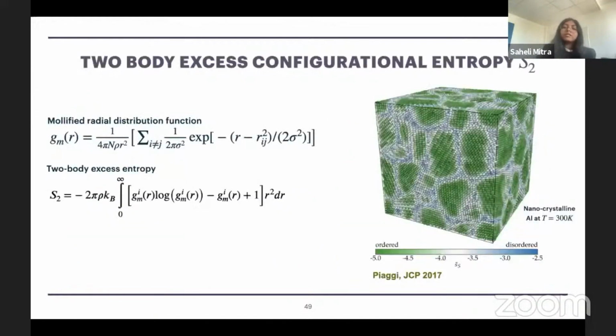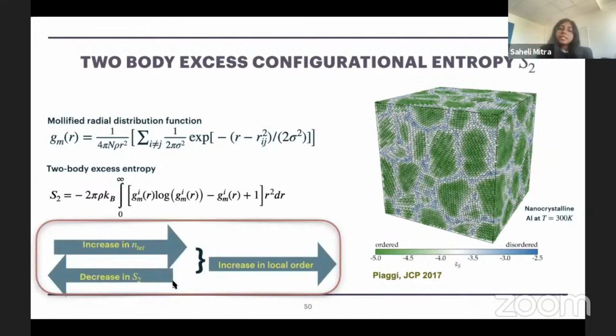Now, the other structural descriptor of our choice is the local entropy S2, which can be calculated from the integration over the local radial distribution function. On the right, I am showing one example for nanocrystalline aluminium, where different phases of ordered and disordered structure can be successfully determined from the S2 calculation. So the takeaway message from tetrahedrality and S2 is this: for a particle, if I have a higher value of tetrahedrality or a lower value of S2, that means at the local level, the structural environment of the system is much more highly ordered.